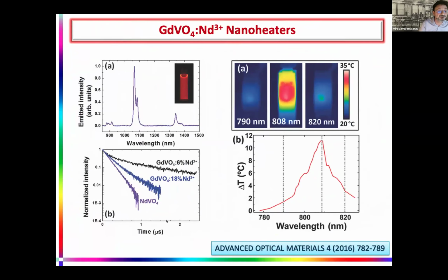So what we did, firstly, we wanted to explore how much heat we can generate with our nanoparticles, and here we have different doping levels. In the lifetime measurements, we can see the lifetime rapidly decreases with the amount of neodymium up to the stoichiometric amount. This means we have huge non-radiative recombination, but still emission, and this non-radiative recombination goes into heat. And you can see here the cuvette with the dispersion of nanoparticles excited by 790, 808, where this absorption is the highest, and 820.